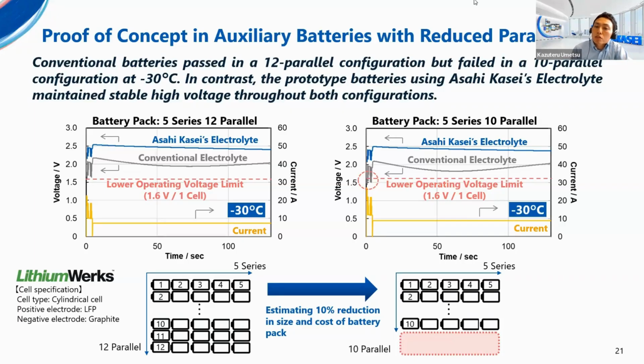We conducted tests with the number of parallel cells in the battery pack reduced from 12 to 10. The current per cell increased, which caused the standard carbonate electrolyte to fall below the lowest voltage limit of 1.6 volt. On the other hand, the acetonitrile-containing electrolyte remained over 1.6 volt thanks to its high ionic conductivity. In this way, the high ionic conductivity of acetonitrile contributes to the size and cost reduction of the battery pack.